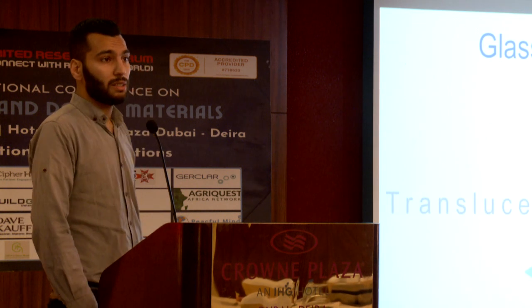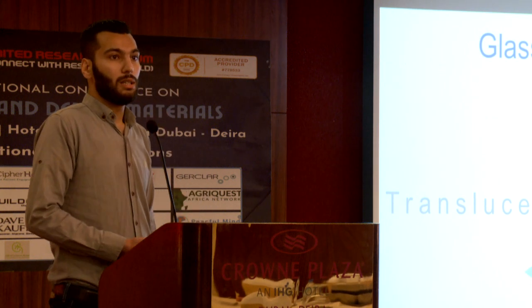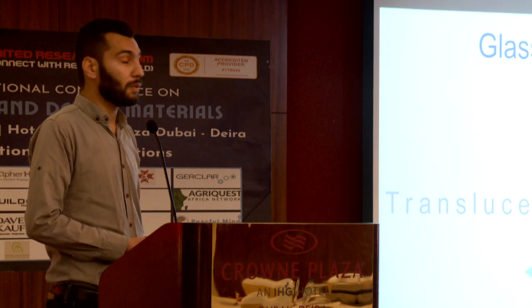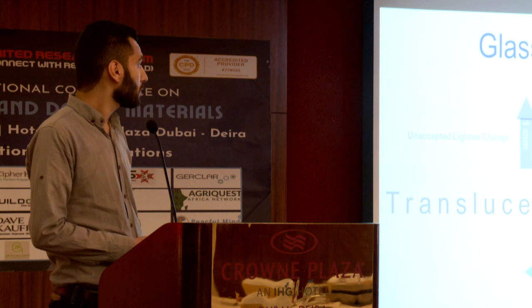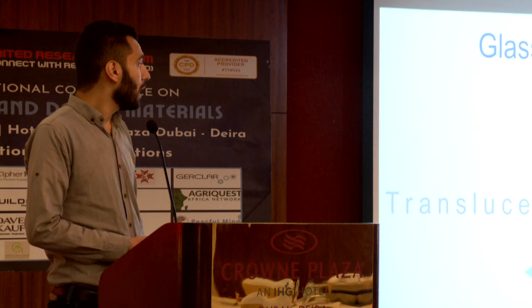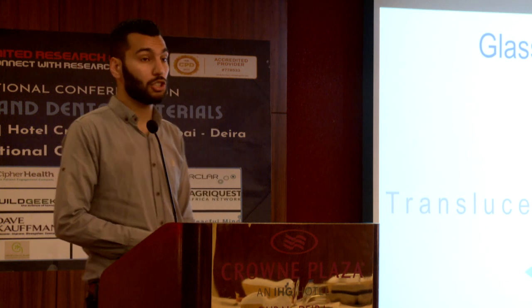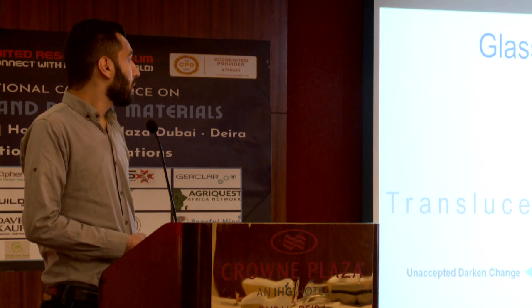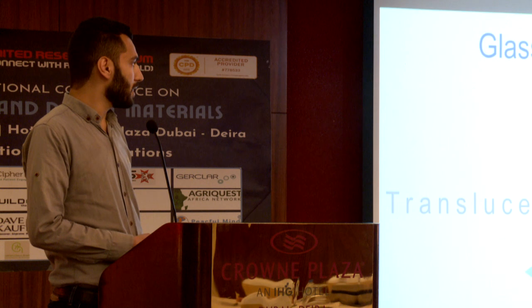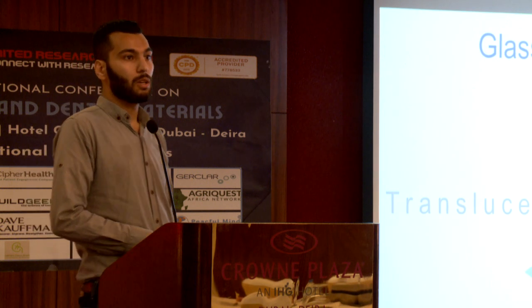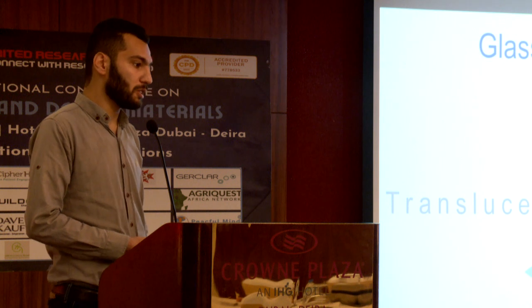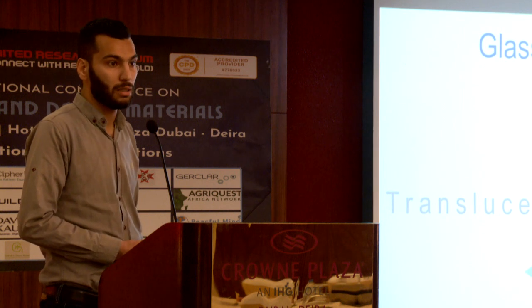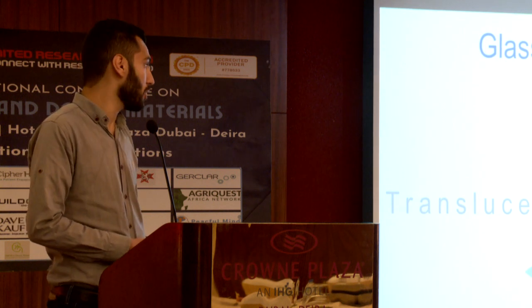The translucent shade of glass matrix ceramic is very affected by all of the resin cements except for the translucent shade. All the resins caused unaccepted shade change for this ceramic, except for the translucent shade resin. What we mean here is, when we choose to use a translucent shade, that means I don't need to shade any background color. It's just for modification of the shade.